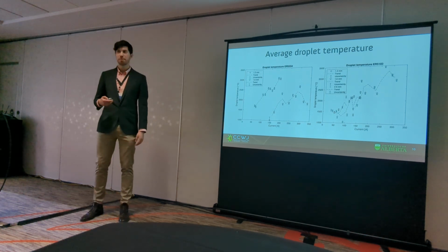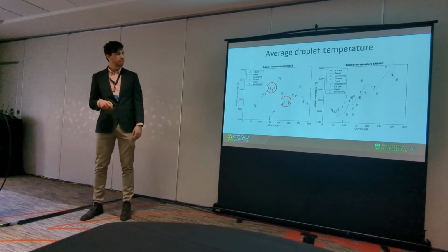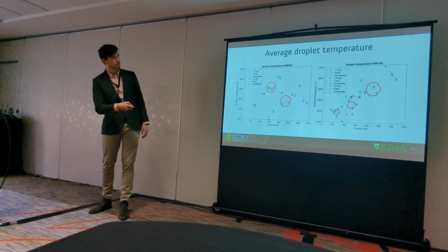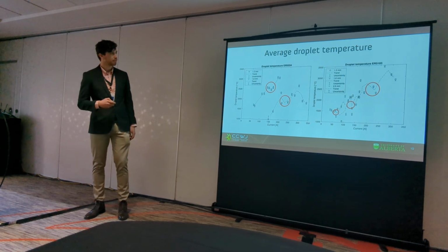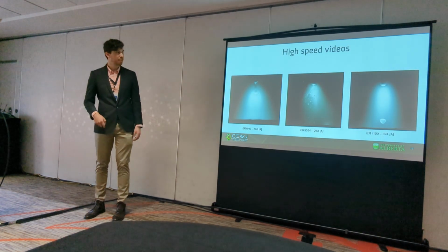But the interesting points are here, the 5554 and 5183, where here at the beginning, the 5554, we have these small dips at the transition current. So between globular and spray, we're going to have a decrease of temperatures. And also in the 5183, we see that in the 3 different diameters, okay? So that's a very important point.